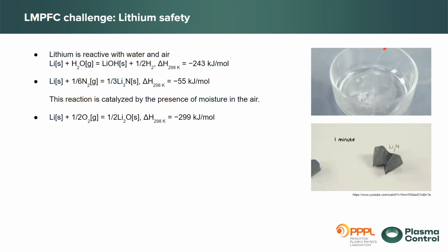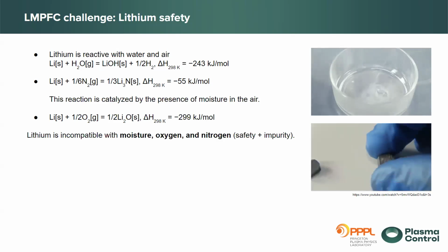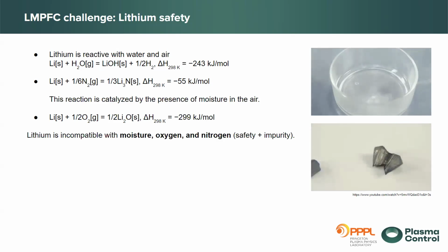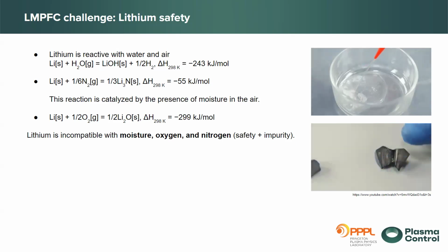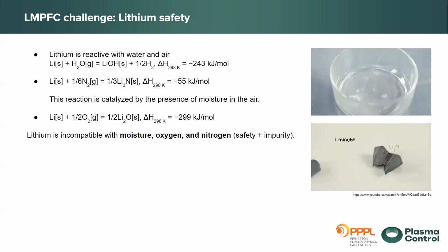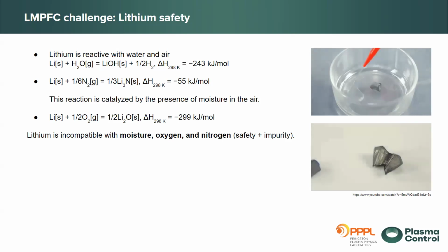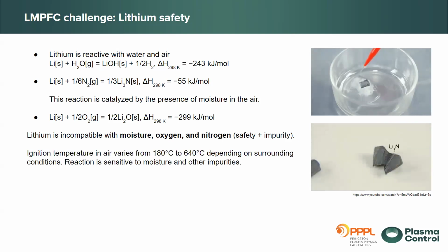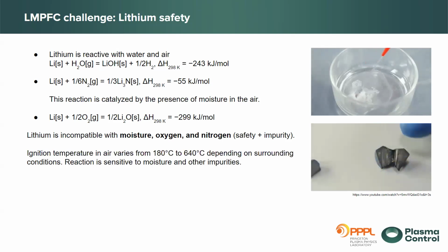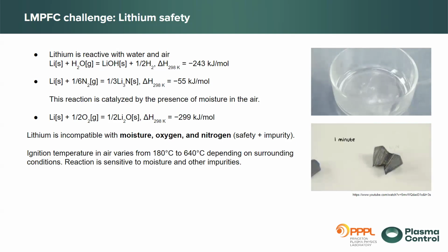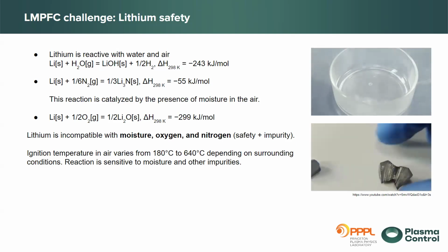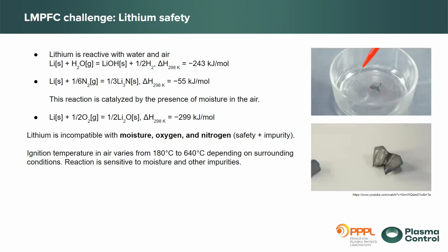Lithium with oxygen will burn, but just to give you a reference, it will probably give out about the same heat as burning firewood. It's on the same order of magnitude. So lithium is incompatible with moisture, oxygen, and nitrogen. That's why we require a working environment that doesn't have too many impurities, including moisture, oxygen, and nitrogen, to guarantee safety.